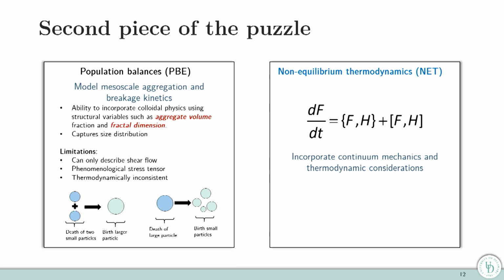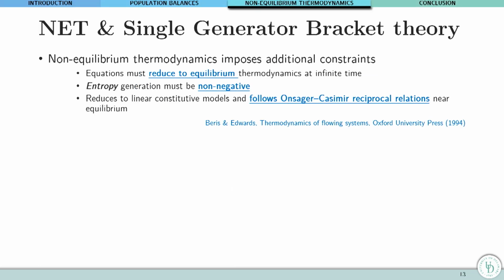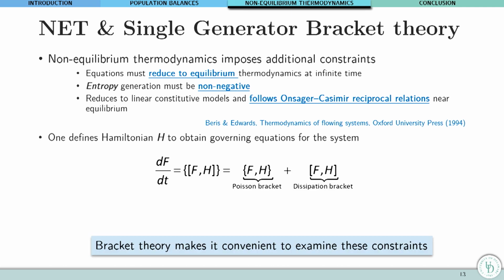Finally, what is the latest development is to incorporate this analysis within a consistent evaluation of the macroscopic equations based on non-equilibrium thermodynamics. I will only take you very quickly through the essence of the theory. It really imposes specific constraints so that, in addition to satisfying, of course, the first law of thermodynamics, the constancy of the Hamiltonian, which is the total energy of the system, the entropy generation is always non-negative, and the dissipation reduces with a perfect satisfaction of the Onsager-Casimir reciprocal relations next to equilibrium.